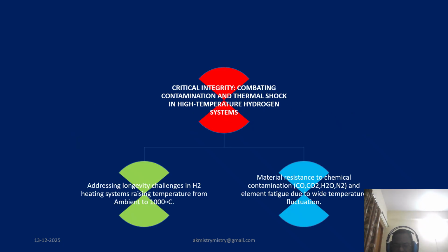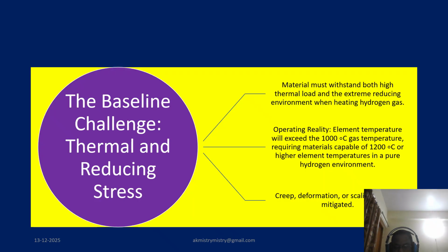Now, as we can see, the baseline challenge is ensuring the material longevity for our heating element to survive and operate reliably. They must simultaneously withstand a high thermal load and the extreme reducing environment inherent in heating hydrogen gas. Given the 1000 degree centigrade target, the element itself will operate significantly hotter, requiring a material capable of 1200 degree centigrade or higher element temperature. In a pure hydrogen environment, if we fail, the result is premature creep, deformation, or scaling.